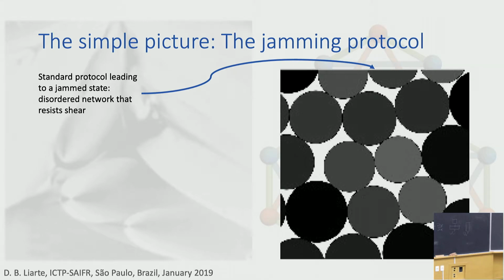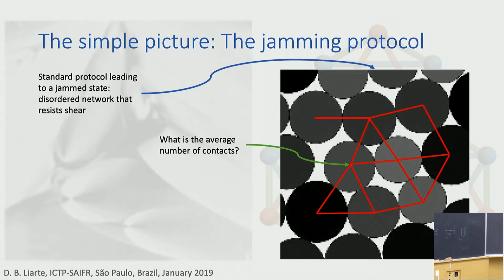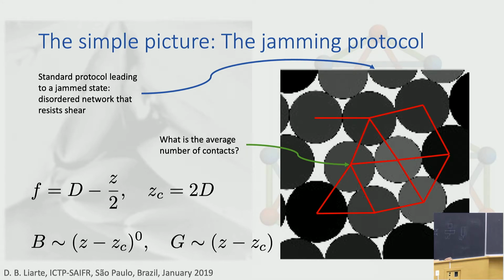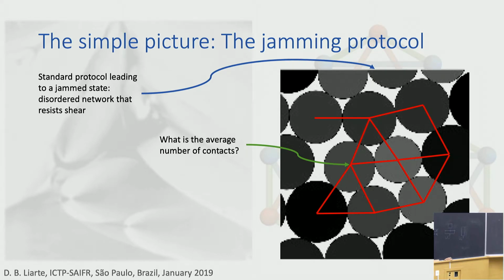One of the interesting things about this is that you can build, for instance, the network of contacts between these spheres or these disks. And it looks pretty much like this. You can count, for instance, the number of contacts for each one of them. This guy here has 4 contacts. This guy has 4. Some will have 3. Some will have 5. The average number will be 4. And there's a good reason for it to be 4. 4 is 2 times the dimension.